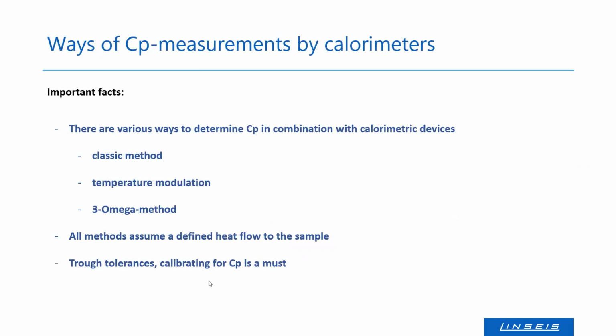Well, there are some different ways to determine the CP with some calorimetric devices. So there's the classic method, the temperature modulation we want to focus on today, and also the 3-omega method. And of course, we measure with DSCs or with calorimeters, and so all of these methods assume a defined heat flow to the sample. That's the main important thing, because basically this is what we can measure with a DSC. And also what's a must here is the calibration for the CP. So we need a reference material whenever you do this calibration, before the measurement or if you set up the device, we have to calibrate the CP through the tolerance of the measurement system itself.